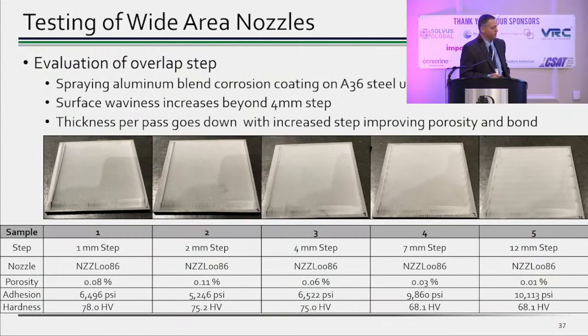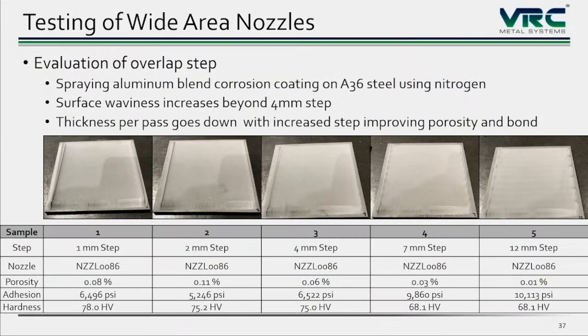So let's take a look at that. If we look at 4 or 5 different step conditions, 1 millimeter step all the way up to a 12 millimeter step, where 1 millimeter is kind of common for a lot of normal nozzles, normal spray processes. We see that we can go all the way up to 4 millimeters, and at this 4 millimeter step condition, we still have a very smooth surface. We have a nice, smooth, uniform surface, and that's because the distribution of particles that we have is still Gaussian. So now you can overlap those, and you can kind of fine-tune that and get a nice, smooth surface.